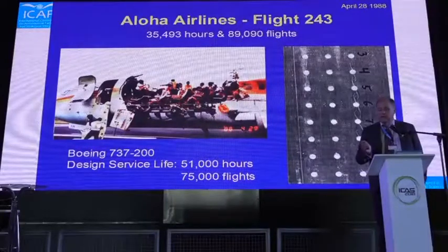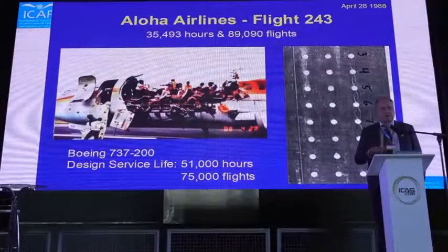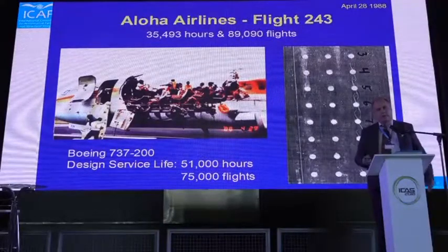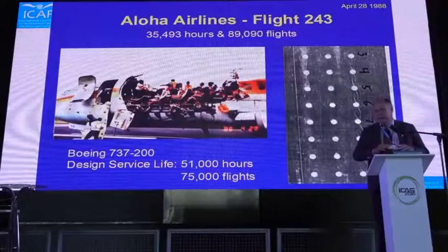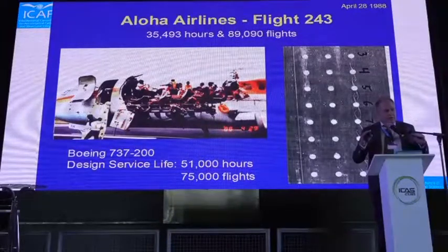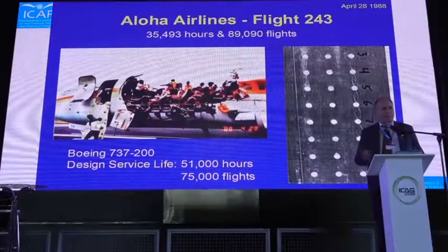And it's particularly important for aging aircraft when you start to fly more than, say, 2 times the original design life. Then you start to get problems with corrosion effects, which will induce small flaws at every single fastener hole. Too small to be found easily, and eventually they can coalesce very quickly.